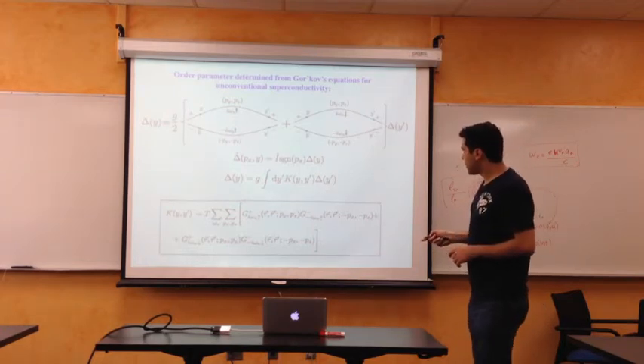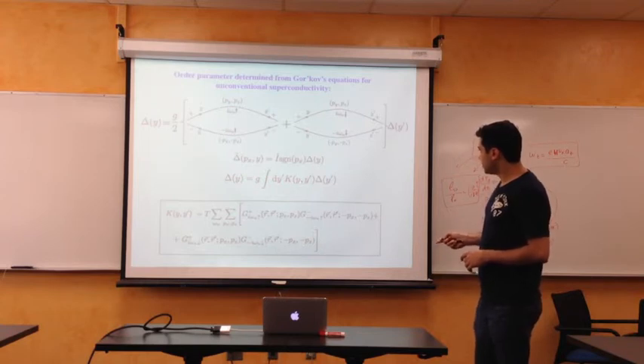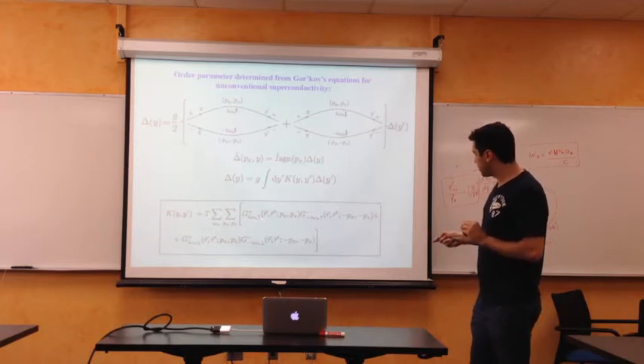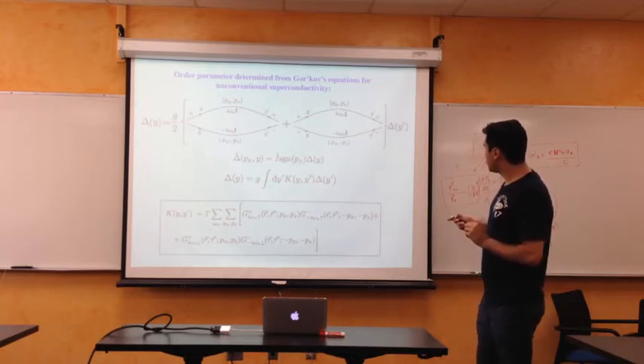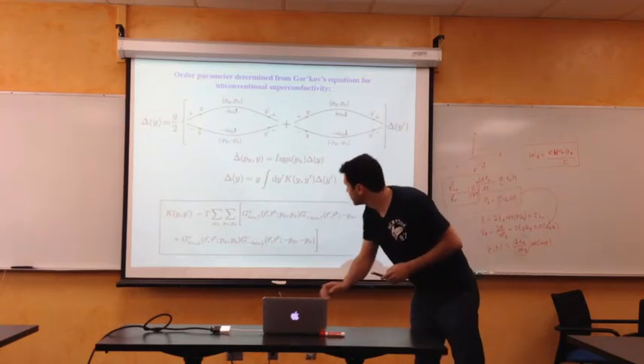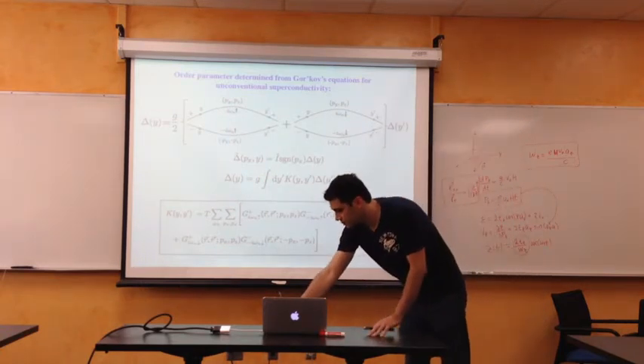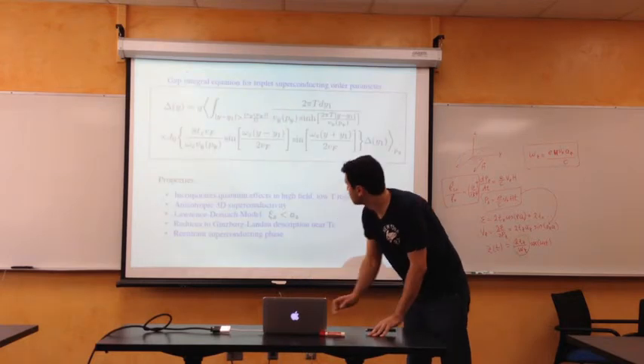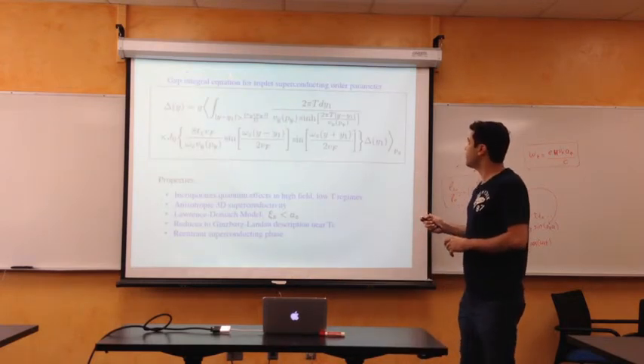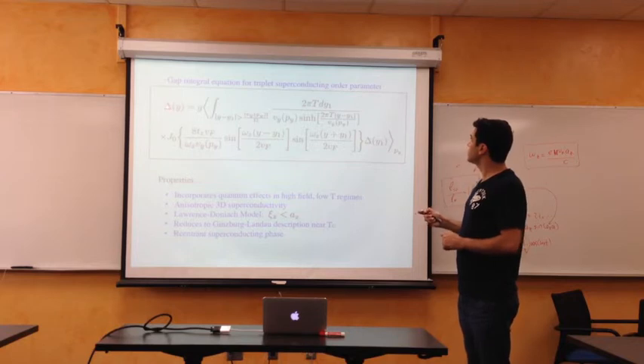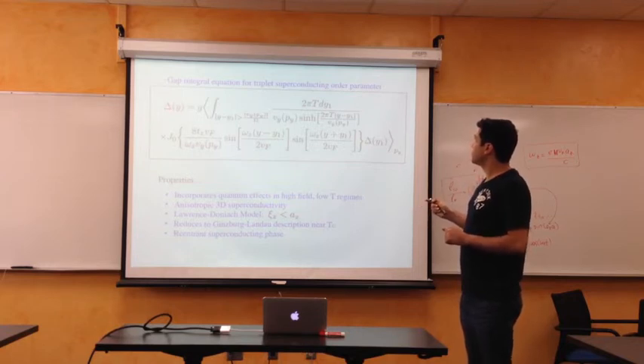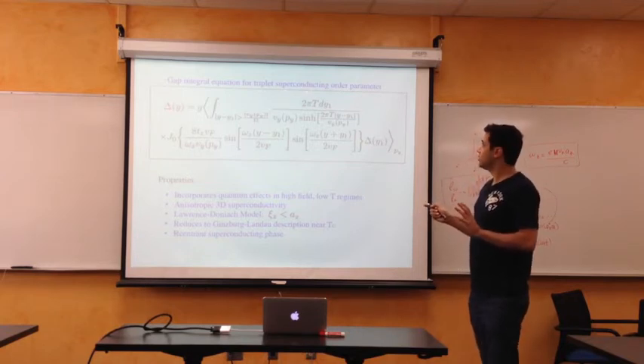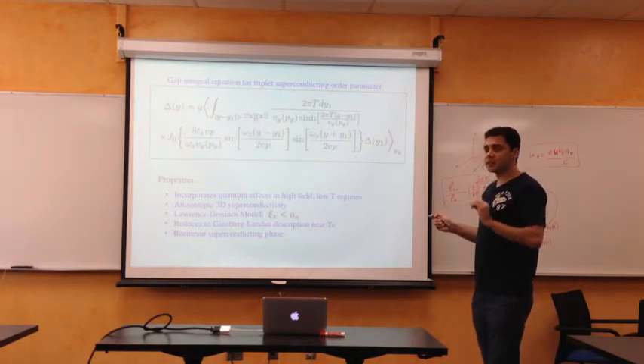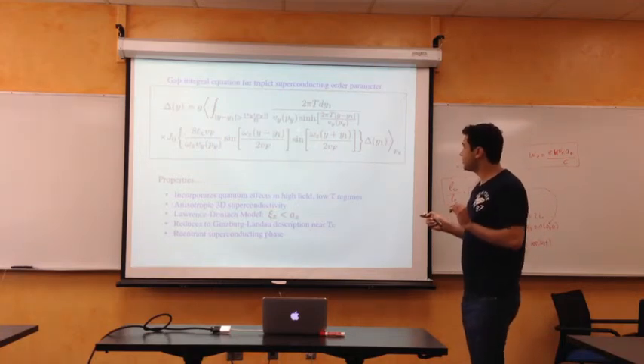So we calculate the kernel here for the integral as a product of Green's functions, and you can see that we include the triplet pairing in the form of up-up plus down-down states. And we arrive at an integral equation for triplet superconductors, which is specifically insensitive to paramagnetic spin splitting effects.